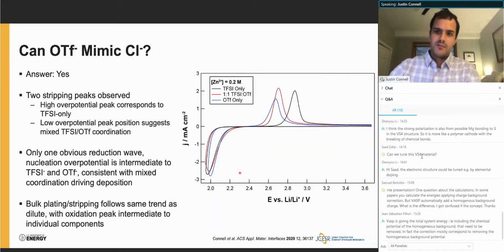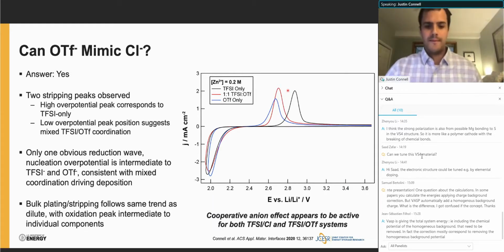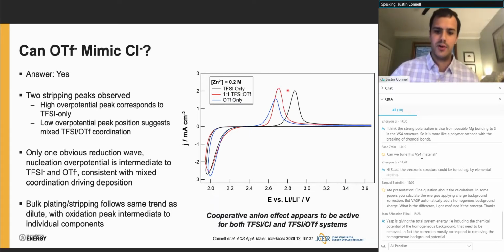Now, this isn't just relevant to the dilute case. If we look now at a bulk electrolyte, a 0.2 molar zinc electrolyte with the TFSI or triflate only, and then the mixed TFSI triflate system, we see essentially the exact same trend, where we see improvement in reversibility relative to both electrolytes and the onset of oxidation, again, sitting intermediate to where we see it for the TFSI only and triflate only cases. And so we have very strong evidence that this cooperative anion effect appears to be active for both the TFSI chloride and the TFSI triflate systems.